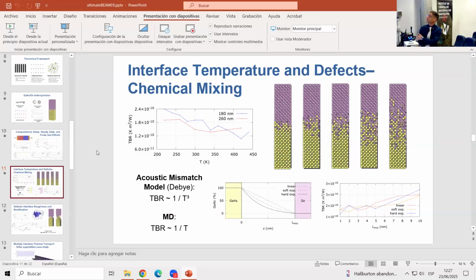Well, here I would say that it is largely due to the random nature of the process we adopted. In my opinion, and I haven't simulated this, if you could make a non-random, regular transition between gallium arsenide and germanium, you would not observe anything like that. You would observe something way richer. Whereas here, you are basically expanding the interface region, where the thermal conductivity is way lower than the thermal conductivity of the two materials.